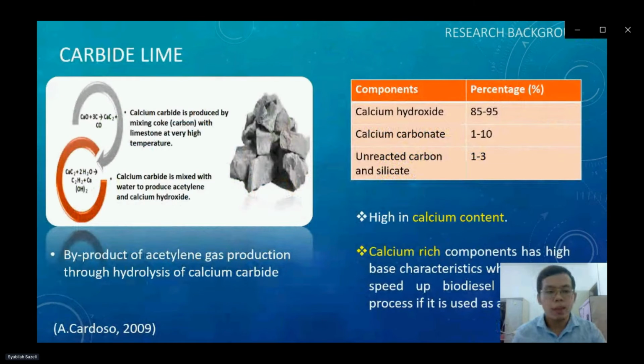Next, I would like to explain about carbide lime. Carbide lime is the material that we will use for the production of the catalyst. The catalyst produced from carbide lime will be used for the production of biodiesel. Carbide lime is the byproduct of acetylene gas production through hydrolysis of calcium carbide. It is high in calcium content; it contains 85 to 95% calcium hydroxide, 1 to 10% calcium carbonate, and 1 to 3% unreacted carbon and silicate. It is confirmed that the calcium-rich component has high base characteristic, which will help to speed up the biodiesel process if it is used as a catalyst.